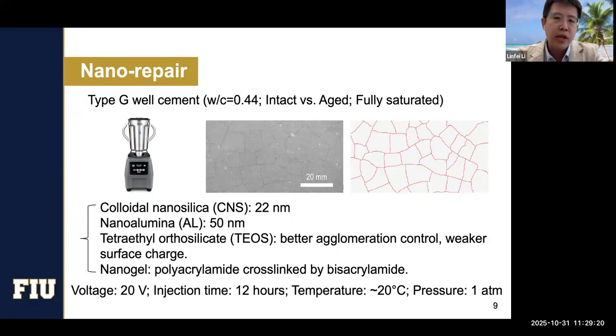We started with an intact sample to see how it works with injection. But at the same time, we also wanted to see what happens if we really have cracks, so we artificially generated some cracks in samples. Then we put the samples in fully saturated, and started running the test. We do not know exactly which nanoparticle will be the best, so we listed a couple of them as candidates.